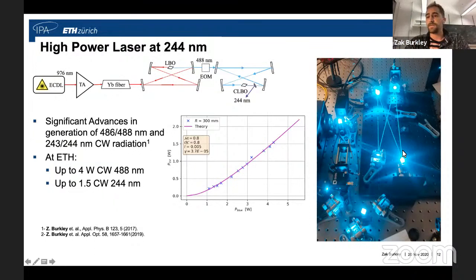And this picture on the right is a picture of our green cavity here before we put in this nonlinear crystal for doubling. Well, 1.5 watts is great. It's much higher than what's really commercially available. It's still not enough. If you remember, this rate was proportional to the intensity squared of the laser. And we still need about an order of magnitude or more power, because that will increase the signal by a factor of 100 to 1,000.